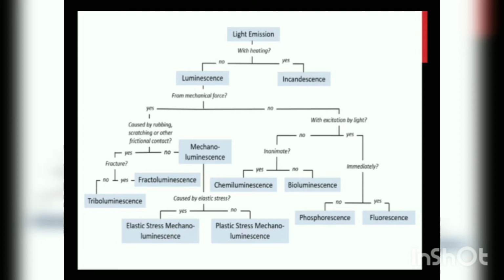This cold emission, that is luminescence, does not include the emission of blackbody radiation and involves two steps: the excitation of the electronic system of the solid material to a higher energy state, and second, the subsequent emission of photons, or simply light. The emission of light takes place at a characteristic time after absorption of the radiation. This parameter allows us to subclassify luminescence into fluorescence and phosphorescence.